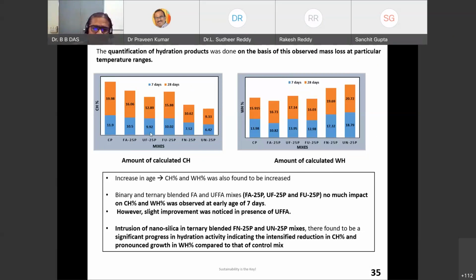Now, similarly, well, this is the reverse phenomenon. You can see here, the moment you add nanoparticles, as compared to the control, even the fly ash mixes, we are getting additional calcium silicate hydrates, and that is going to benefit me. That is going to be a bonus for me. So whatever I spoke actually, binary and ternary blended fly ashes, ultrafine fly ash, had no much impact on percentage of calcium hydroxide and WH% observed at early age of 7 days. However, slight improvement is noticed in presence of ultrafine fly ash. But integral nano silica and ternary blended mixes found a significant progress in hydration activity, indicating intensified reduction in percentage of calcium hydroxide and pronounced growth in WH percentages compared to that of control. Okay, that is basically the technical language, but I explained it to you very normally.